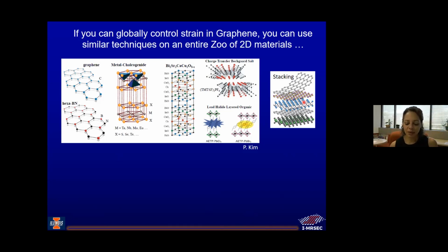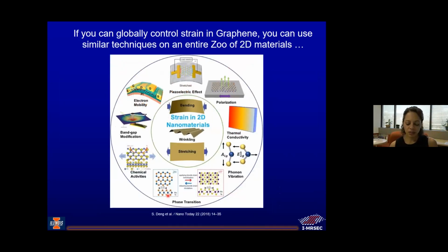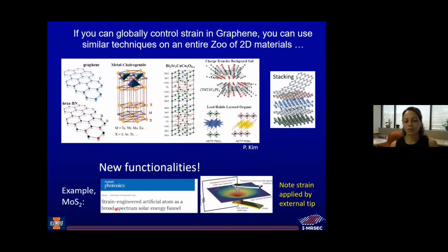And just as an example of an effect, this is a paper that came out some time ago. It's showing how if you take molybdenum disulfide and you strain it locally, it becomes a really good solar energy funnel. Okay, so they put an electrode on top, and they could actually funnel light into this little region that was highly strained. But note here, they did this by applying strain with just a single external AFM tip. Okay, so again, if you can do this globally, you can get a device out of it.